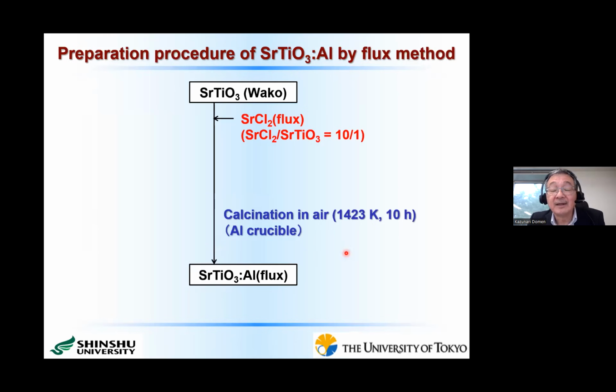But of course, we further try to modify this method. Of course, we intentionally introduce alumina into these flux materials. But I should say that this added alumina seems not to work as a dopant, but it seems to work as a shape controlling reagent. Let me show the evidence for that.